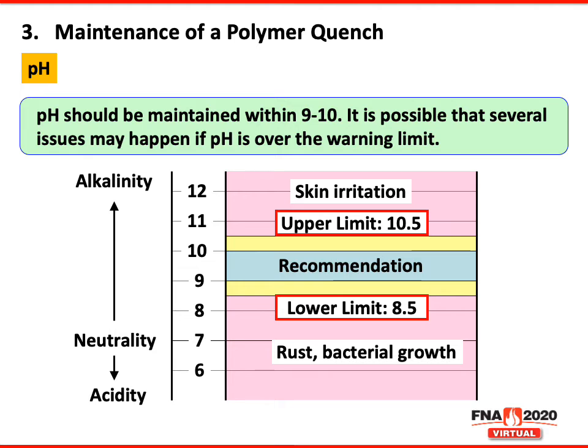We talked about bacteria and pH. Well, this slide shows that you want to keep your pH between 8.5 and 10.5, because below that you can have rust and growth of bacteria. Above it, operators that are very sensitive will start to have skin irritation. And the higher the pH goes, the more people will have irritation to the polymer quench.